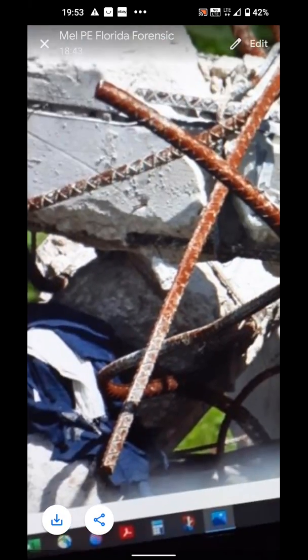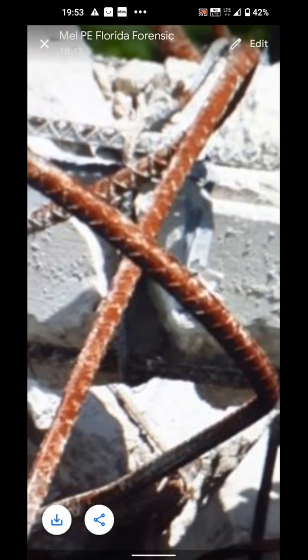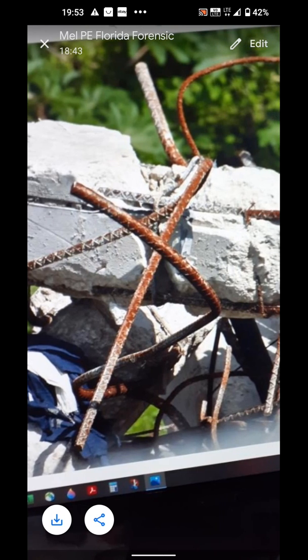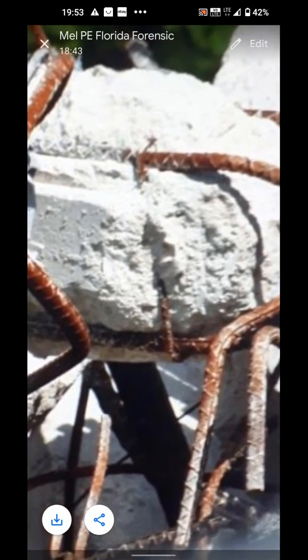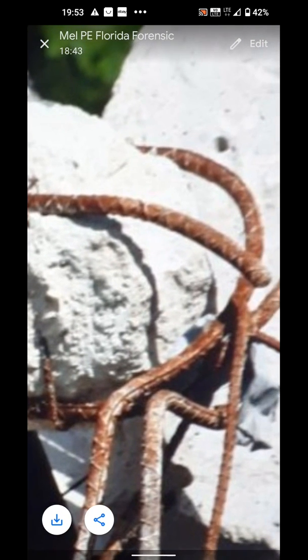We've got some paste at the end here, but then there's a large amount of rust — no paste means no interaction, no bond with the concrete. Those are stirrups, the little guys right there. Some spalling took place as it came down. There's a stirrup at the top with a little bit of concrete over the top of it, which is cool — it tells you how it performed.